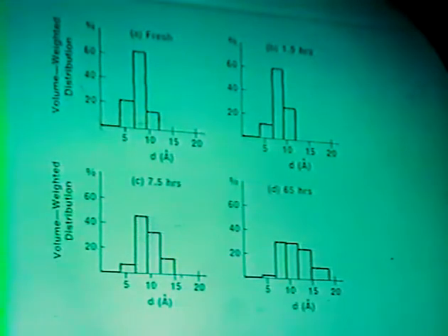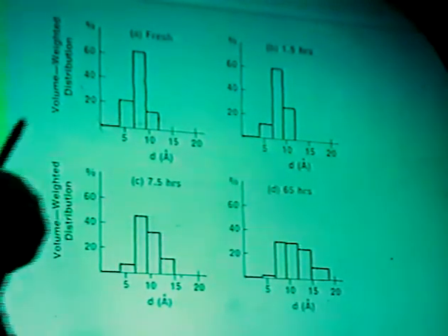The other point I should have made is that at the end of those poisoning experiments, they had added only about 1/10 sulfur atom per platinum atom. If it were simply blocking of the surface, you would have had very little poisoning. But the small amount of sulfur catalyzes this particle growth and causes the platinum to move outside the L zeolite.